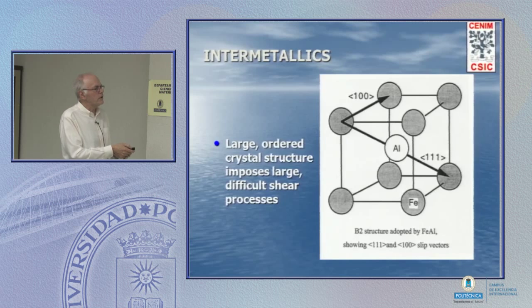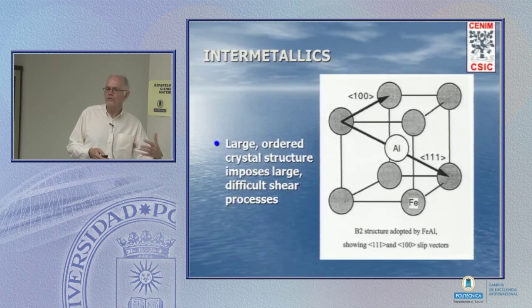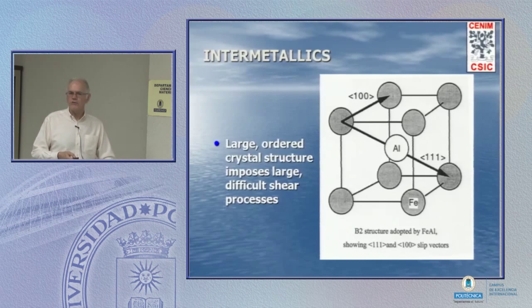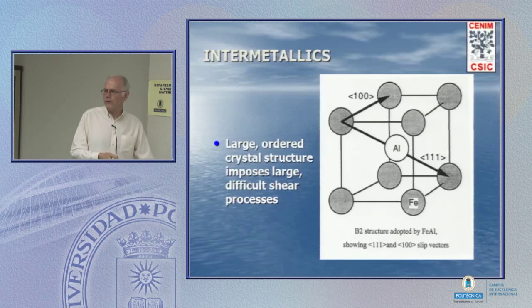We've got two alternatives. We can double up. Instead of having a half 1, 1, 1, we have a full 1, 1, 1 vector. Or we can go to a 1, 0, 0 vector. In both cases, they're larger vectors. Energy of dislocation goes with b squared. So they're much more energetic. They're more difficult to produce.